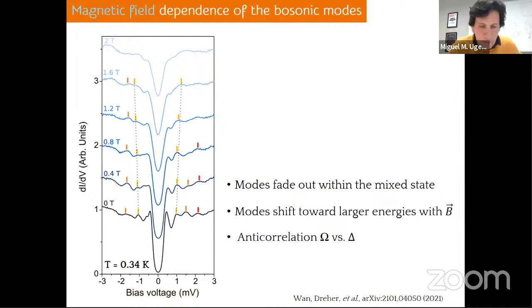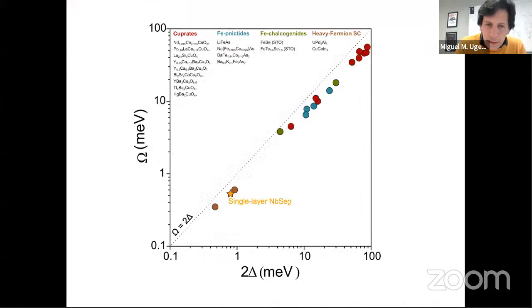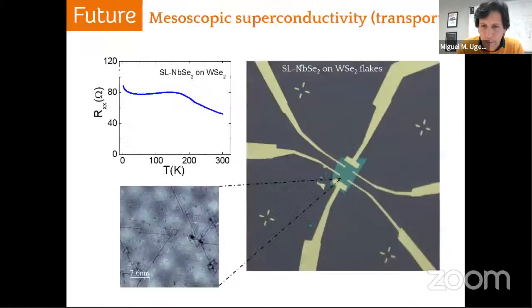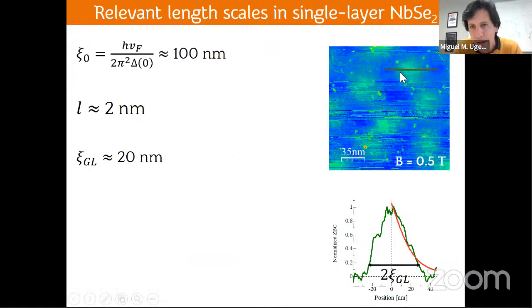So Herman, you have a very sharp eye, and that's totally true. We have done this series of measurements in different positions, trying to be in the superconducting region. The initial plan was to image the vortices, but that has been extremely difficult for us. The only time we succeeded was in this image, where you can see the typical size of the vortices, but it was fairly impossible. So we decided to try to do the same sets in different locations. That's one part of the explanation.